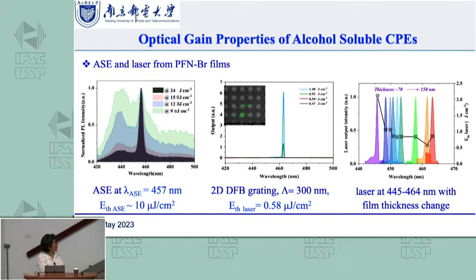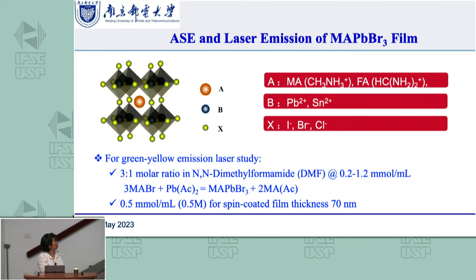So we put this onto the two-dimensional laser grating. We can make the laser from this material. That just shows you when we change the thickness, the laser peak moved from 445 to 464. So this is the result from this alcohol soluble material.